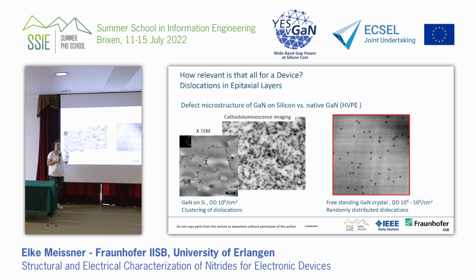the material does not emit light. And then you can prove, which you have to do of course, like with the etching, that at places where dislocations are, you have no emission of light, so that these dark places are really places of dislocation. Then you can do correlative analysis with defect etching, and at such places you don't find emission of light. So you see, for example, here, cathodoluminescence imaging of gallium nitride on silicon, which has 10 to the 9 dislocations per square centimeter, and you see that all these places are defects.